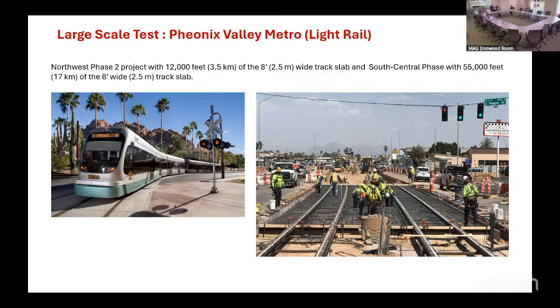The idea of taking all of the rebar out and replacing it with steel fiber came up at a meeting where I was proposing to do hybrid design, just take half of the rebar. And they challenged me to verify that we can actually take all of the rebar out. The problem with this type of an application is because of the DC current that we have for the light rail that generates potential corrosion cracking in the rebar. So you have to have everything welded together, all of the specs and all of those things to be handled.